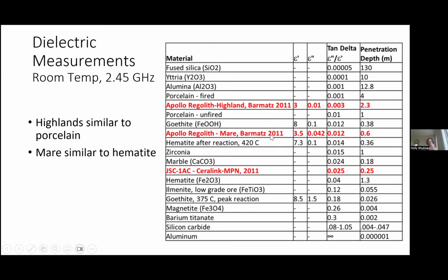This material really acts like a basalt. So I can look at the dielectric properties as a function of temperature. This is just a snapshot at room temperature, and get a real sense of other materials that I've worked with and understand how this is going to behave, at least dielectrically, not necessarily physically and how it sinters. And this is where JSC-1A, and this was actually 1AC, fits in. It's a reasonable proximity to the mare sample that Marty Barmatz measured.